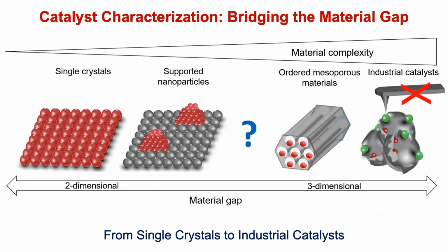And that is shown here in this slide, where you really show this materials gap, going from single crystals to supported nanoparticles or mesoporous materials. And I'm quite sure that Naresh will agree that with industrial catalysts it will not be easy to use tip-enhanced Raman spectroscopy, because your surface flatness will prevent you from getting good samples measured with this technique. So it shows that STM, AFM, and whatever methods will not be so applicable to the right type of catalyst, and very well to the left. On the other hand, with techniques like synchrotron methods, I think you can do a lot of interesting studies on catalysts.